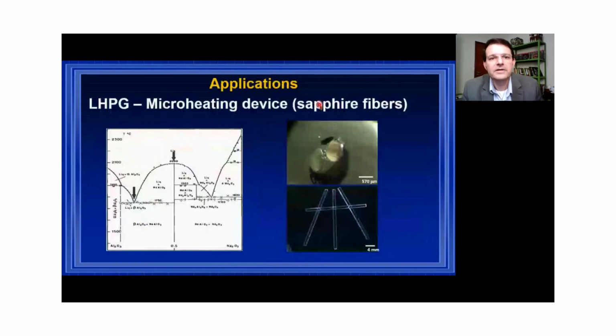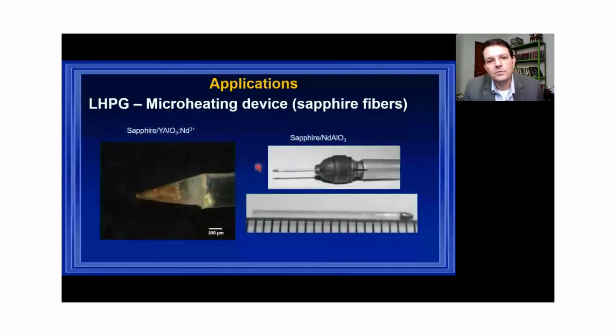For the micro heating devices, we use sapphire fibers to guide the light. If you put rare earth in the sapphire, you know it will all segregate to the liquid, and you get pure sapphire. But if you grow on top of the sapphire optical fiber, you can grow a different compound with a very high concentration of rare earth.